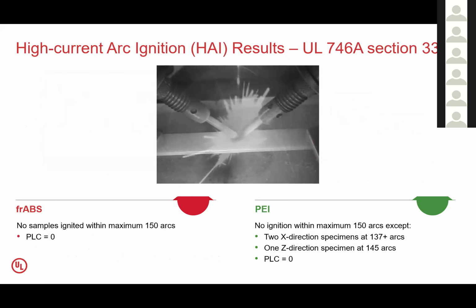When we look at high current arc ignition, so this is simulating between two live components, there may be some arc occurring when, like, a switch, for instance. So we're looking for up to 150 arcs being subjected to the surface of the material. Will it cause the material to ignite? And we found with the ABS material, regardless of how we printed it, or if it was injection molded, none of our specimens ignited. So they all get the best rating, best performance level categorization, which is great.